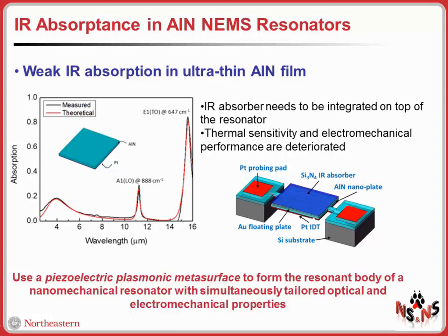The way we are trying to solve this fundamental issue is to instead use a piezoelectric plasmonic metasurface to form the resonant body of a nanomechanical resonator with simultaneously tailored optical and electromechanical properties. The idea here is to pattern the electrodes of the device in such a way as to simultaneously excite an optical and electromechanical resonance in the same ultra-thin piezoelectric material. And then, by exploiting the intrinsically high thermomechanical coupling between these two resonances, we can achieve high sensitivity to infrared radiation.